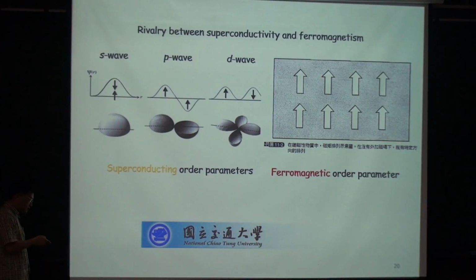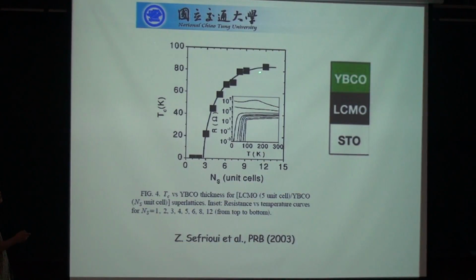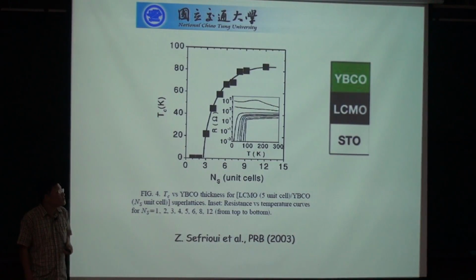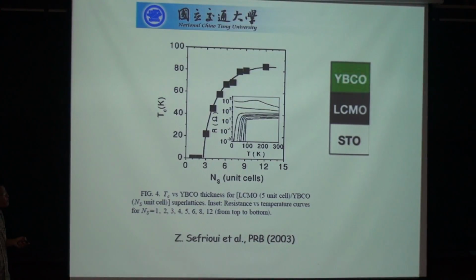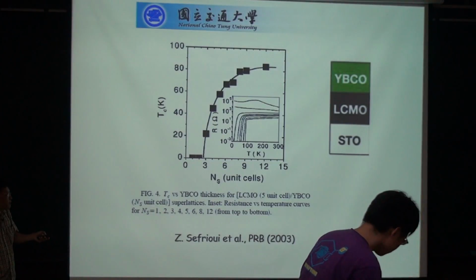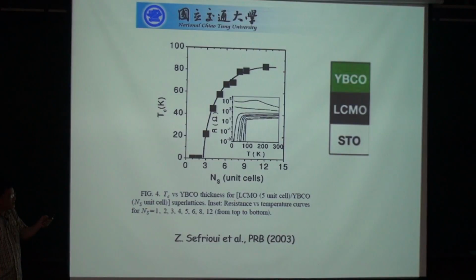And indeed, when you put these two things together, you can see this is the TC of the bulk material for YBCO. When you combine these two things, once the ferromagnetism becomes relatively stronger and stronger, the superconducting temperature just goes down. In a way, these two kinds of order, superconducting order and ferromagnetic order, do not like each other. They even compete with each other and want to kill each other. That's the main idea. But we like conflict, right? In the scientific community we like conflict and try to get something new from the conflict. That's the motivation to put these two things together. And as I have already told you, this is not new. This has been for more than one decade that people have made this kind of bilayer system.